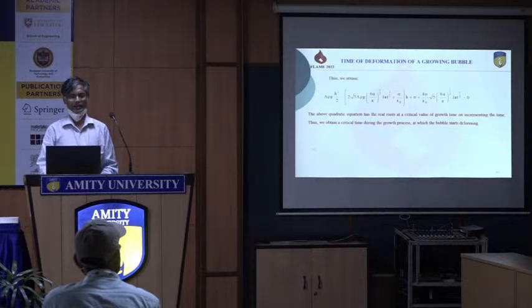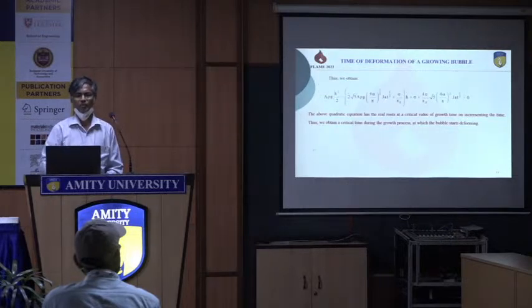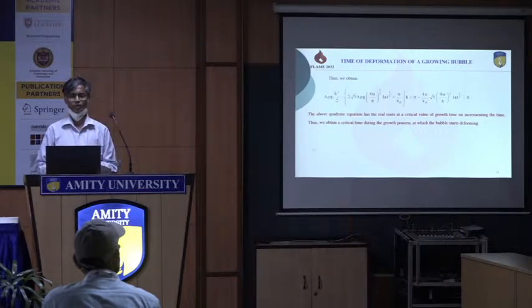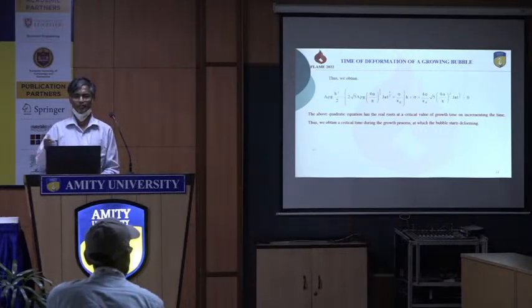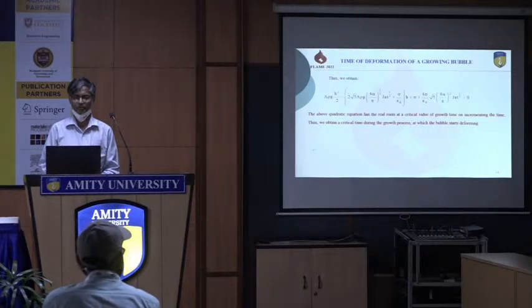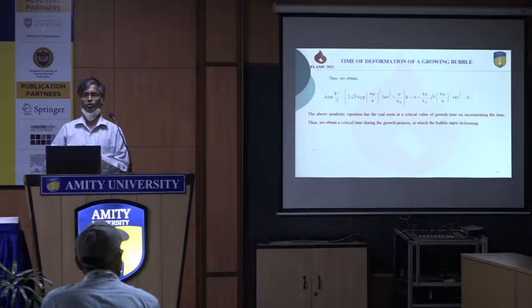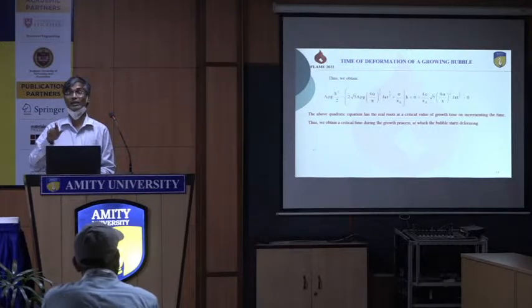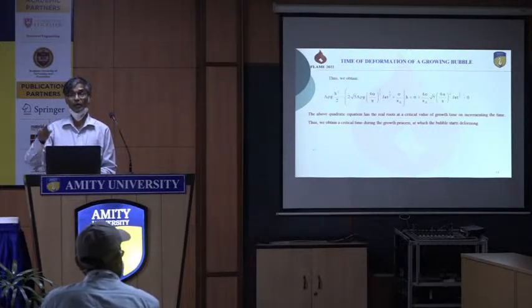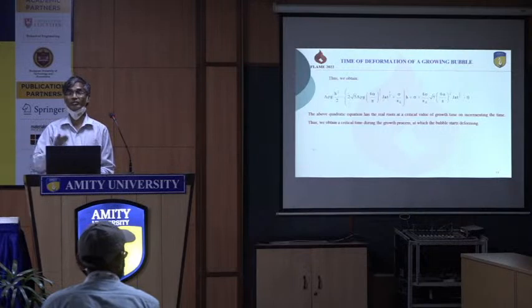At the same time, this force balance equation is solved by putting in the theory of bubble dynamics or bubble growth. This quadratic equation will give you the real solution at time t when the bubble is deforming. Otherwise, it will give an imaginary solution. So that indicates that deformation is there.